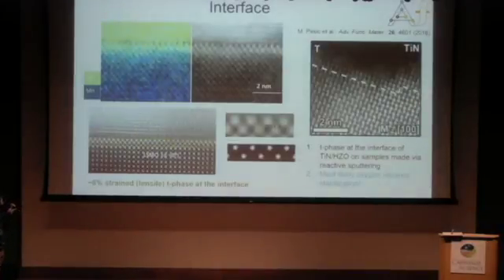Okay, so finally, let me talk about the interface. So the interface, these are the chemical maps, and we see that at the interface between LSMO and HZO, we have a different phase of HZO itself, and that is in fact a tetragonal phase, a T phase, which grows in the 001 direction, but it is completely epitaxially strained with respect to the substrate. So there is an 8% tensile strain T phase, which extends for 2 to 3 monolayers. Okay, so what is happening, right?